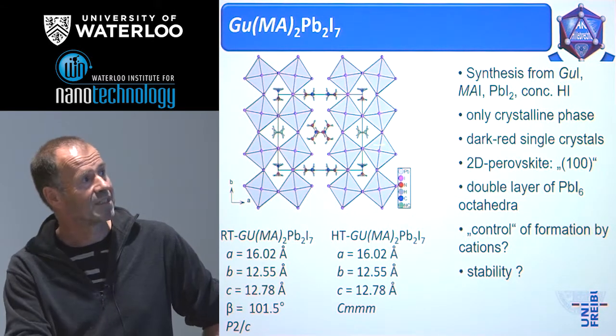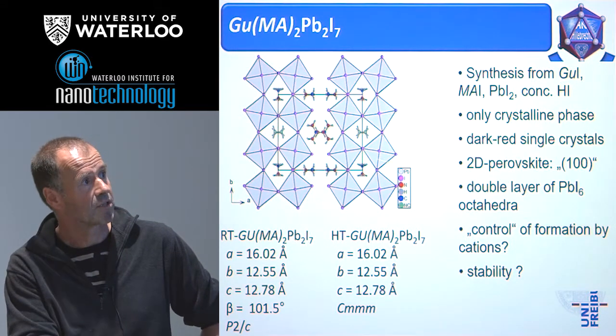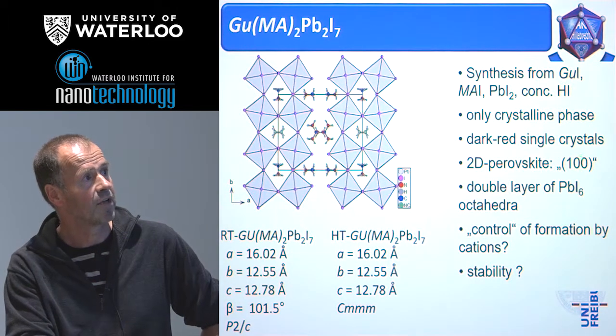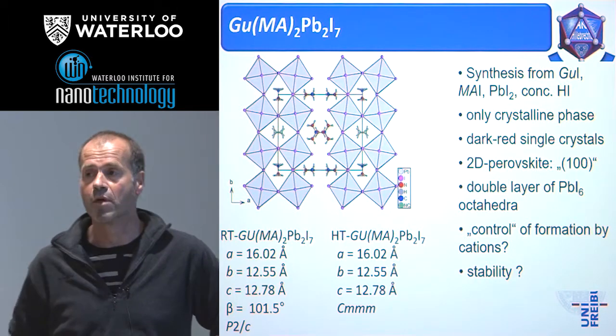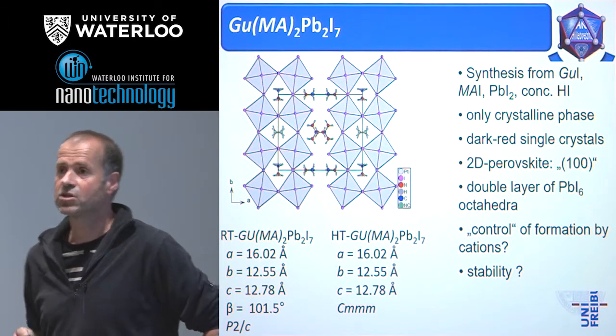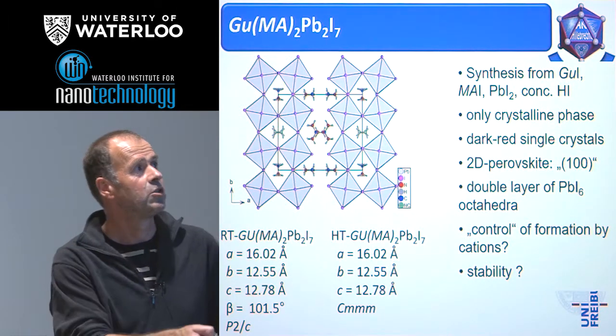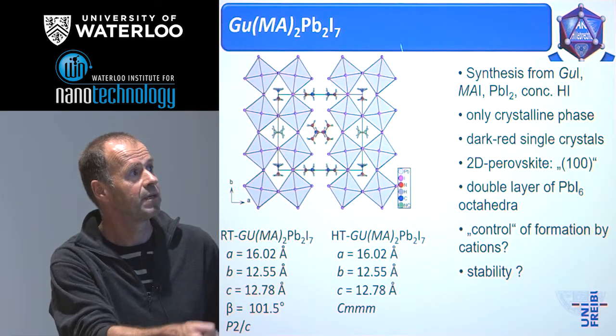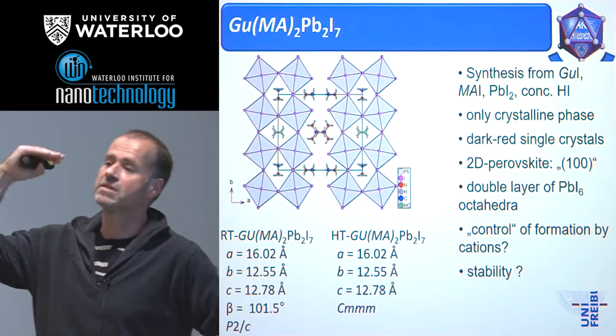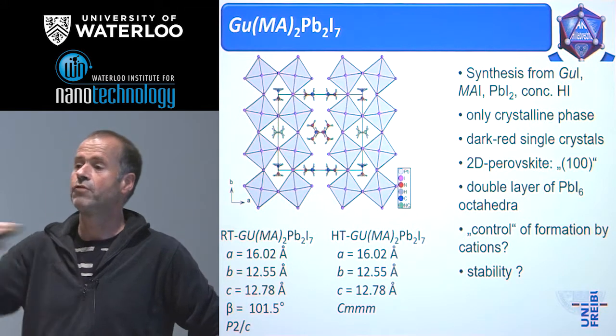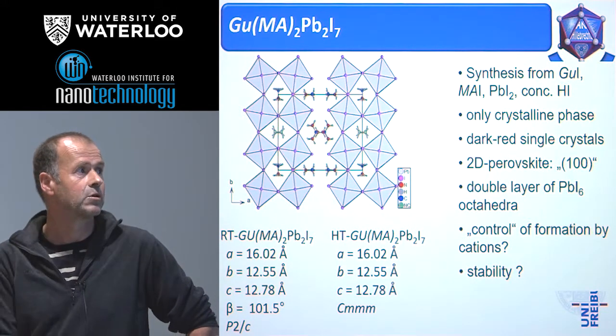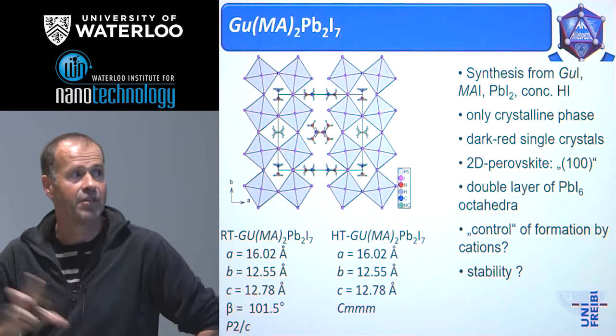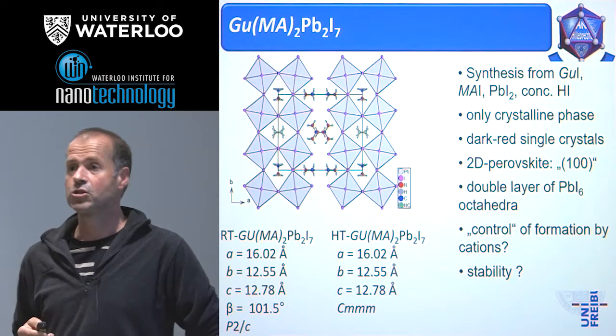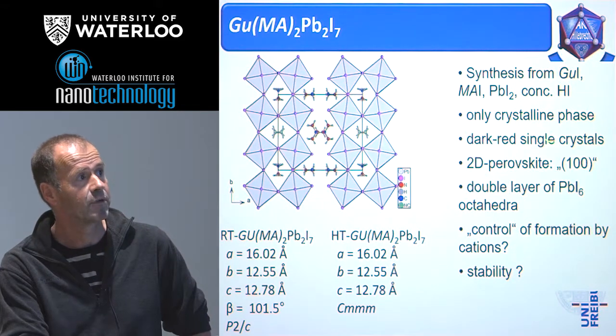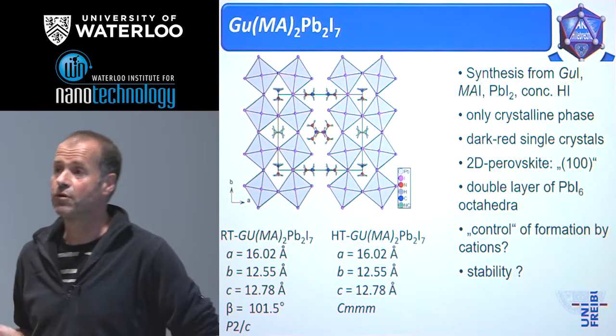The crystal structure is, in my view, quite simple. It's a so-called 2D perovskite according to the direction 1, 0, 0. If you imagine the cubic structure of the perovskite, you just take a slice of the cubic structure according to the crystallographic direction 100, following the a lattice parameter, and now you combine 2 of these layers and the story is complete. It should be mentioned that we get dark red crystals. That means we have a first impression of the band gap.